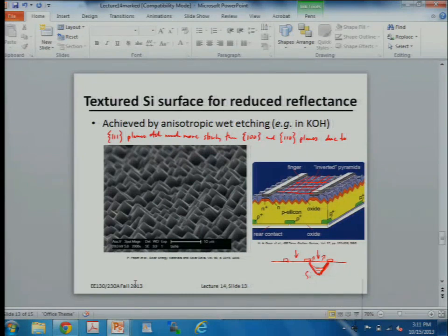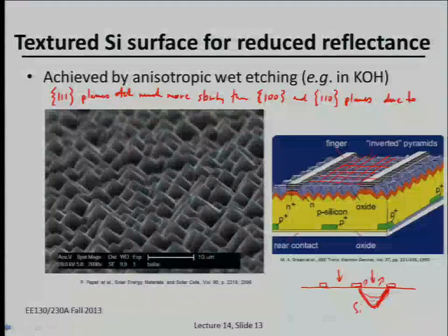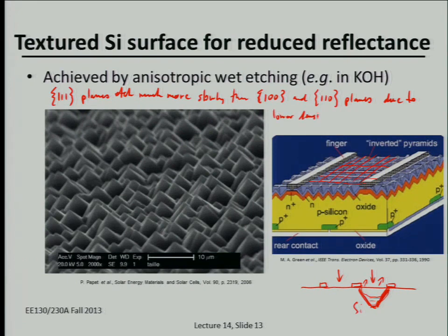Okay, so to finish this sentence, it's due to a lower density of dangling bonds for reaction with OH. Okay, so like if the bonds are kind of sideways, it's easier to break them to have a reaction with OH.